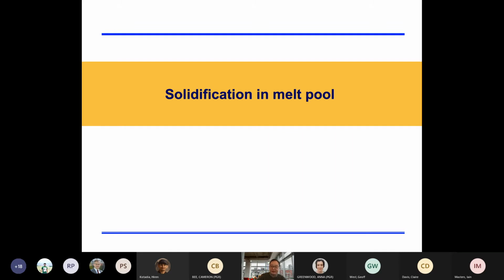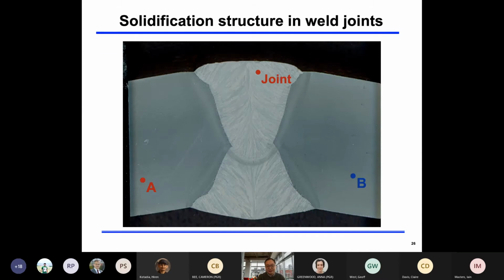Today I will talk about solidification more, not so much solid state transformation, but look into how liquid transforms to solid, right? We look at the grain structure level, and normally we'll see very fine grains around the interfaces, right? And then in the center zone you will have some columnar grains growing, and normally in the center you have some equiaxed grains forming.